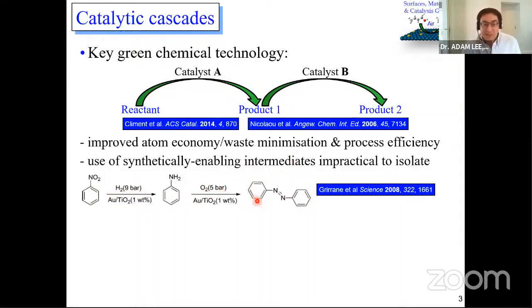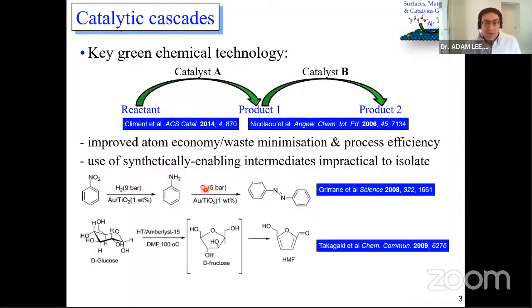This is an example which is easy because it's the same catalyst, but is also potentially dangerous because you have a high pressure of hydrogen and you have to purge that very carefully from the reactor before you introduce oxygen to avoid an explosion. You can have reactions that are cascades that involve acid and base chemistry.